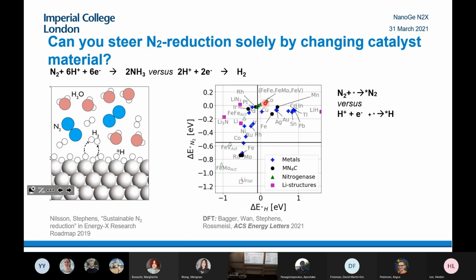So if you look here, this is the nitrogen binding energy as a function of hydrogen binding. So if you had a really, really selective catalyst that could work in principle in an aqueous solution, what would happen? It would bind nitrogen really strongly and hydrogen weakly. So it would be in this quadrant here. Well, what we can actually see is that no surface is in this quadrant. Not metals, not metal doped carbons, not even lithium mediated structures, which we found actually work experimentally.